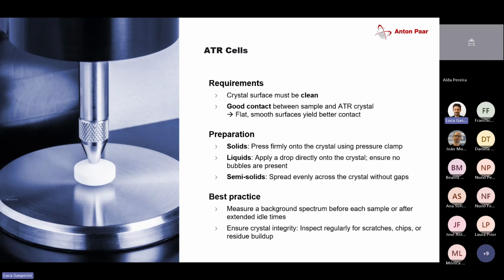As I said, these instruments are very, very sensitive. So even moisture or CO2 will be picked up by the instrument. So what you do is you record all of the external influences. The instrument saves this as a background, and then it will subtract the background from the actual sample, so that you only see the sample, not anything else.